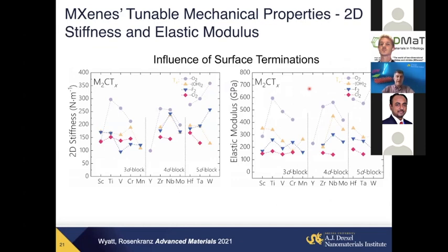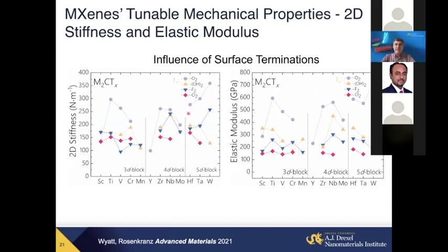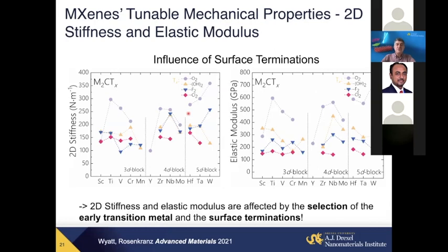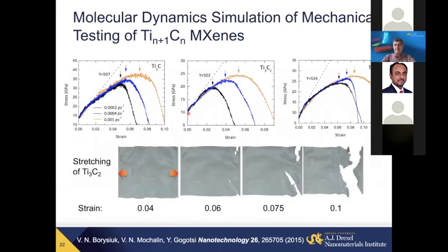Andreas was very kind to provide several slides to me from his research. As you can see, this is an example of stiffness and moduli changing for M2C structures, which are the thinnest of MXenes available, as a function of surface termination. So whether we put oxygen, OH, fluorine, chlorine, those properties change. So again, we have a tunable family of materials. You may design material with properties that you need for applications. Select transition metal, change surface termination, get the material.